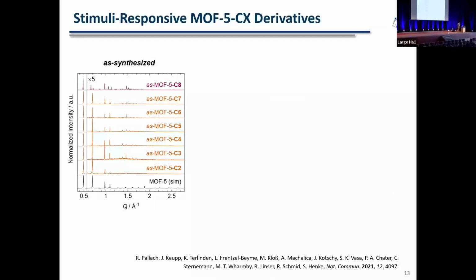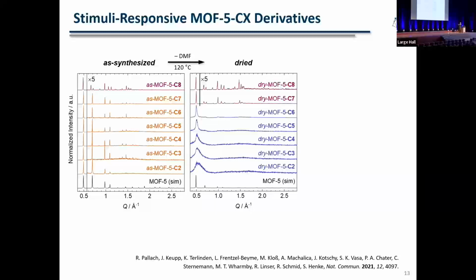Okay, now these have been the synthesized materials, with solvent molecules in the pores, which also solvate these side chains. When we now take the guest out, something weird happens. First of all, for the material with a C7 chain, you go from the cubic to also the rhombohedral state. So it contracts as well, a little bit more even than the C8, and you have a rhombohedral structure. For the smaller side chains, yeah, as a synthetic chemist, you would say, okay, the structure collapsed and we just throw it into the bin. What most people did in the past, I think.